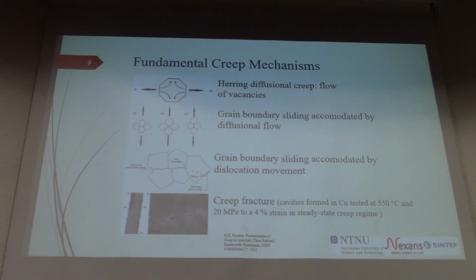Creep mechanism might be due to diffusional flows of vacancies and sliding of the grain boundary, or dislocational flow, or we can also have creep nucleation of fractures and propagation, time-dependent crack propagation.